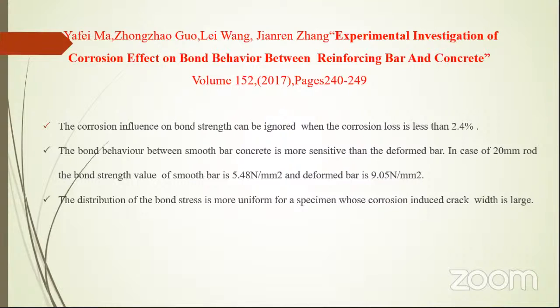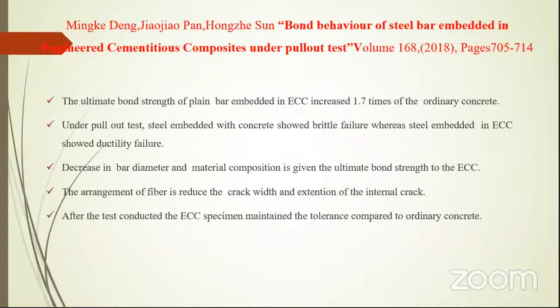The next paper is about experimental investigation of corrosion effect on bond behavior between reinforcing bar and concrete. In this, the corrosion influence on bond strength can be ignored when the corrosion loss is less than 2.4%. The bond behavior between smooth bar and concrete is more sensitive than the deformed bar. In the case of a 20 mm rod, the bond strength value of smooth bar is 5.48 Newton per mm² and deformed bar is about 9.05 Newton per mm². The distribution of bond stress is more uniform for the specimen whose corrosion-induced crack width is large.